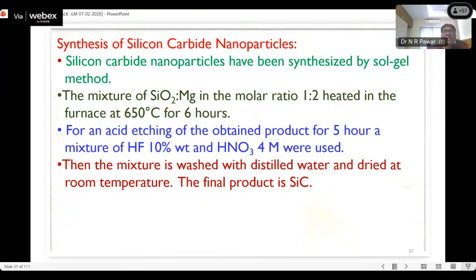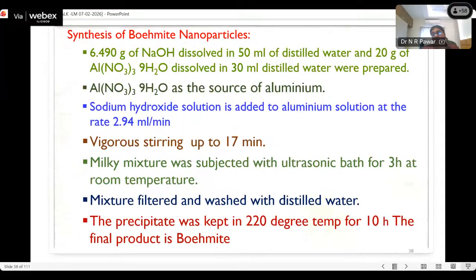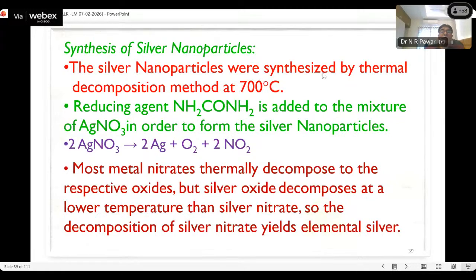This is the synthesis of silicon carbide nanoparticles. Okay, this we have also synthesized by the sol-gel technique. Second is the boehmite nanoparticle. This nanoparticle plays very important roles for various applications in various fields. And this we have also synthesized, and one of my research scholars was awarded a PhD on this topic. And then silver nanoparticle. The silver nanoparticle was synthesized by the thermal decomposition method at 700 degrees Celsius.